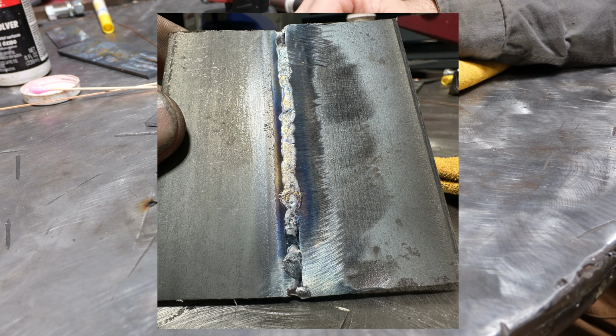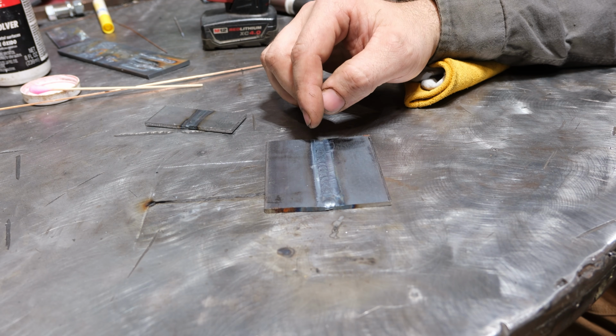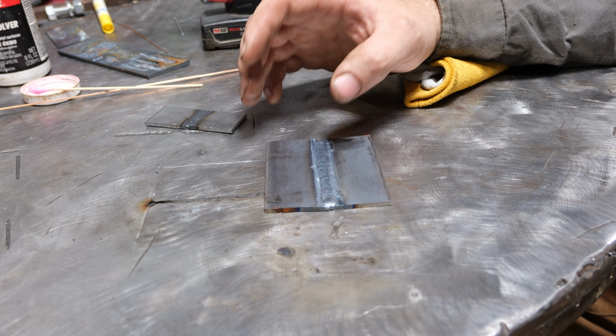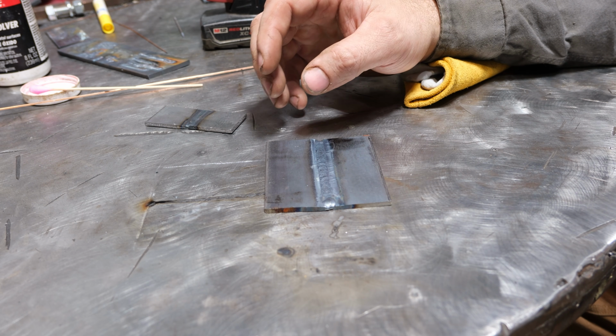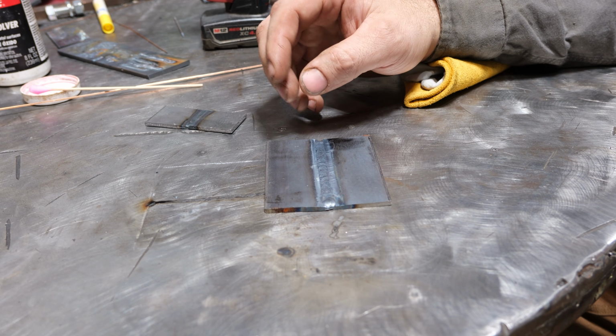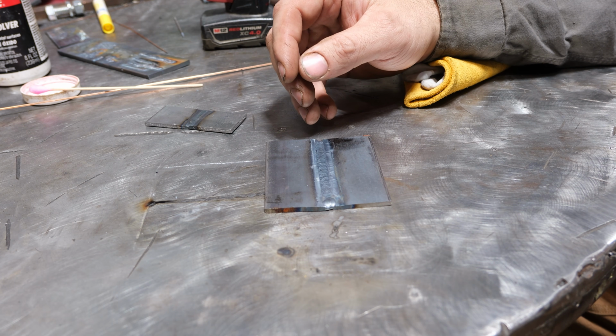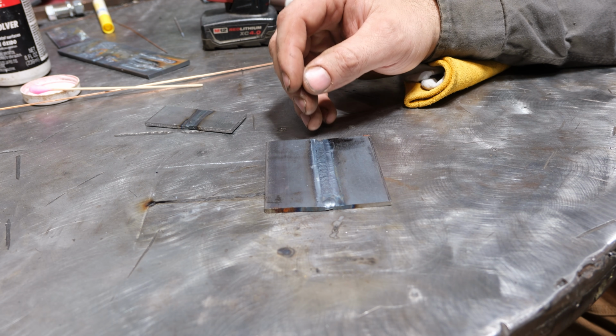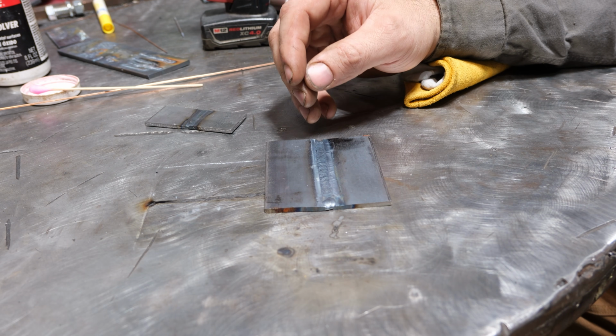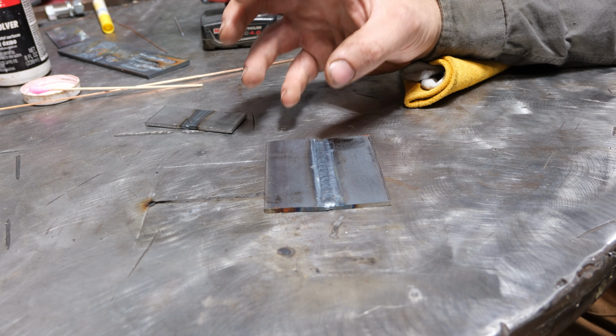What you don't want to do in this case is run less amperage and run cold to where you have reinforcement on the face of it, but no penetration or fusion through it. And that's probably the biggest mistake I find people doing with open gaps, is they reduce the amperage. They're able to make a nice looking weld that protrudes off the face so it looks like you have reinforcement, but you simply don't have any penetration or fusion, and you more or less have a bead sitting like caulk on the face of it. So you're always better off running hot enough to where you know the bead is sunk in there and has penetrated and fused something.